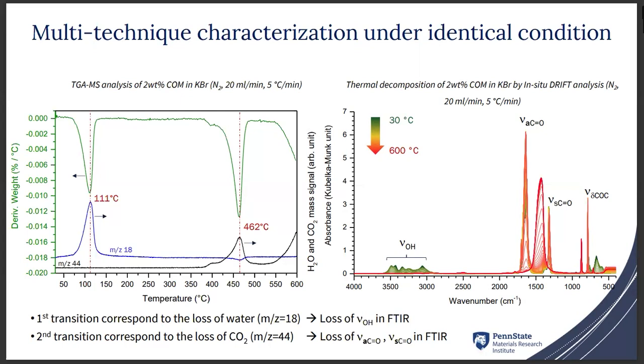We look at, under the same condition, the FTIR of these 2 weight percent calcium oxalate monohydrate in potassium bromide, and we can see the decrease of the hydroxyl band by FTIR and a change of the carbonyl band for the compound.